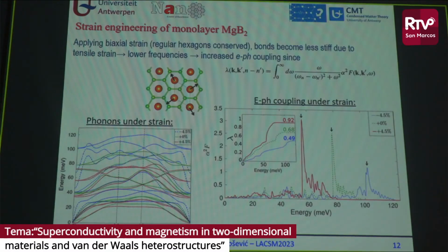Now, what happens when we strain this material? So, when we strain, this is a biaxial strain, so I'm just making these hexagons larger. I'm preserving the symmetry. Bonds will become less stiff. That means lower frequencies of my phonons. So this is the positive tensile strain, red compared to green, shifts to lower energies. You see that? Because of that, the electron-phonon coupling shifts to lower frequencies and becomes larger, just because of this frequency dependence. So basically, I'm increasing superconducting electron-phonon coupling by the biaxial strain.